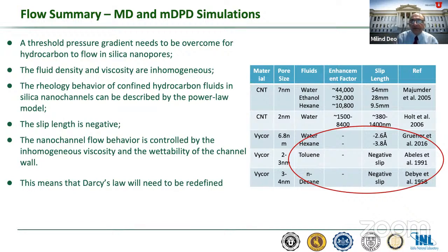Another takeaway is that the flow is affected by how the fluid actually interacts with the wall. That means that single phase permeability will not be the same and will need to be adjusted depending on how strong those wall surface interactions are. That means that we will have to make an adjustment to single phase Darcy's law. And then of course, we have to take it from there to the multiphase. So I think this is a fairly significant finding. We do have to quantify this effect more thoroughly, but this is what we are seeing with the multiple pieces of evidence that I presented to you.